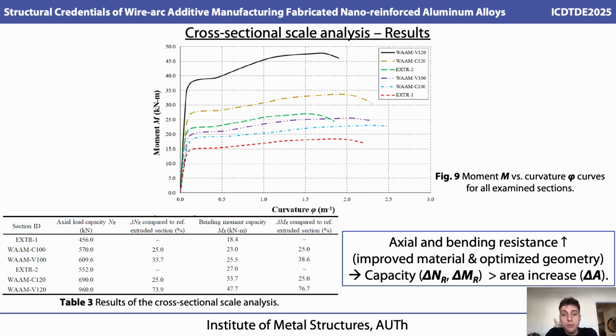In figure 9, we can see the results of the moment versus curvature analysis through the moment versus curvature curves for all the examined sections. As you can see, we get higher moment resistance and curvatures for the sections featuring both WAM production and the nano treatment of the material. As you can see, we reach up to 76.7% bending moment increase, and we reach up to 73.9% increase in the axial load capacity. This happens due to both the material improvement and the optimized geometries when we use the variable thickness sections. The capacity gains are higher than the area gains, where the area gain is 7% and 40% for the two sections respectively.